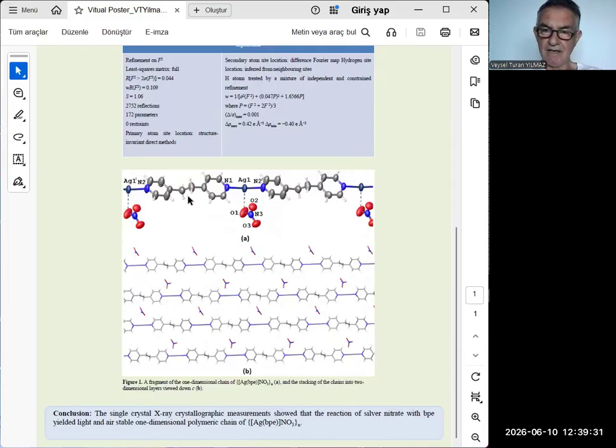The coordination environment around silver ions seems to be linear, with an N-Ag-N bond angle of approximately 172 degrees. However, the distance between the silver ion and one of the oxygens of the nitrate ion is only 2.75 angstrom, which is an important distance to say that there is an interaction between the nitrate ion and silver ions. We call this a semi-coordination of the nitrate ion with the silver ion.